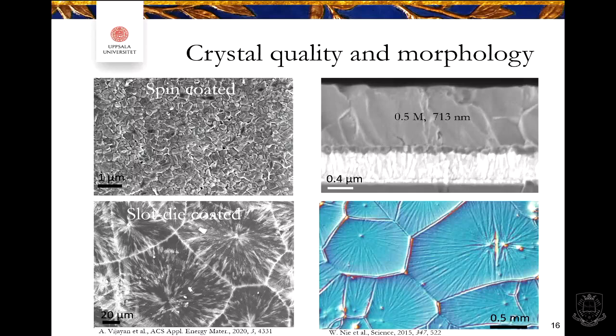Yeah, so we published a paper in 2020, but here we found a rather old paper of also a large-scale deposition technique, but it was not slot die coating, I don't remember which one it was, which looked rather similar to what we saw. So even though it looks very strange, you can get a rather good efficiency, but you also get a much more inhomogeneous surface. And that inhomogeneous surface is one of the reasons why we get these hysteresis effects, which I will talk about later on.